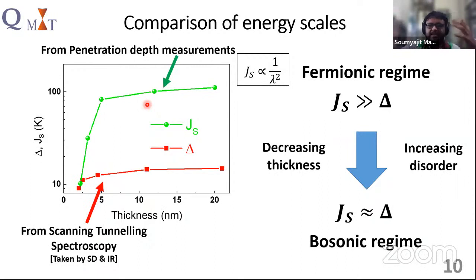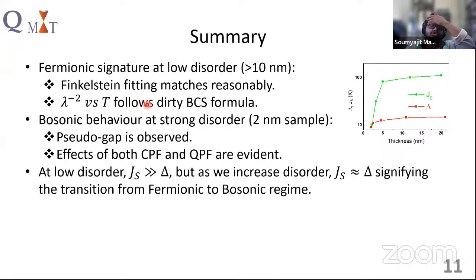So it means that it becomes more and more susceptible to phase fluctuation. So this picture portrays very beautifully the transition from the fermionic regime to the bosonic regime. So to summarize, we have seen the fermionic signature at the higher thickness samples, and the bosonic behavior at the lowest thickness sample, and also in this curve we could see the transition in the two energy scales. Thank you.